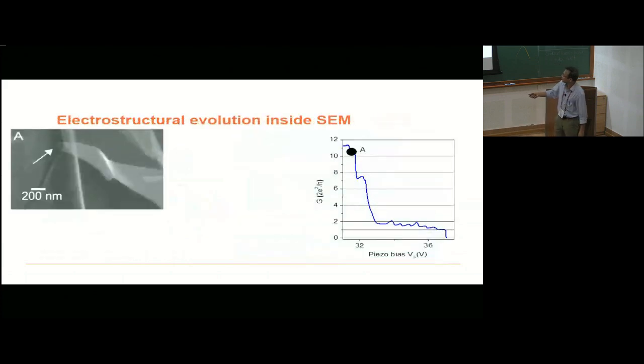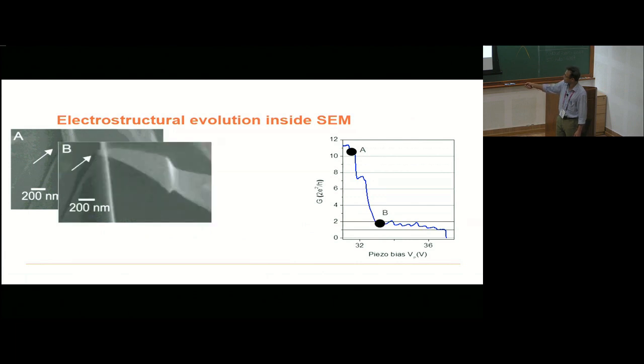Again, very quickly, this is how it looks like. This is where the tearing is taking place. You can see this is the contact between the graphene and the substrate underneath, and you can see that when there is a huge contact area, the conductance is very large. If you tear farther, the contact area is decreasing, and conductance is decreasing too. This is the conductance of this point contact over here.